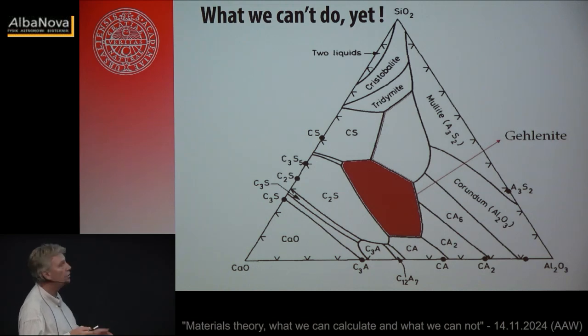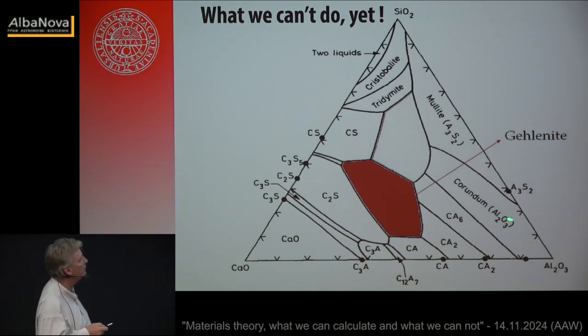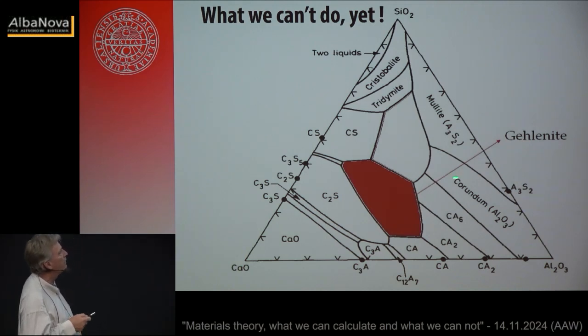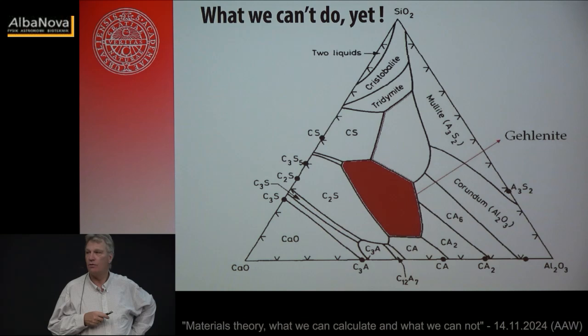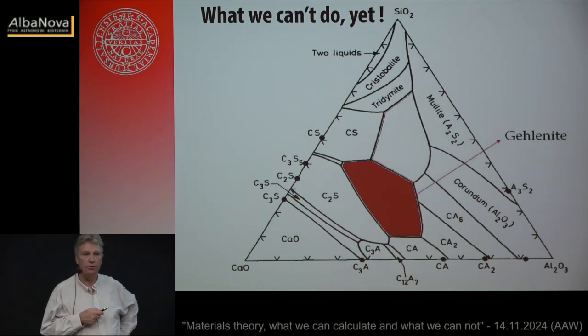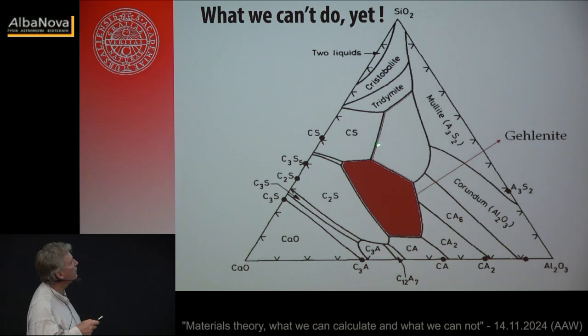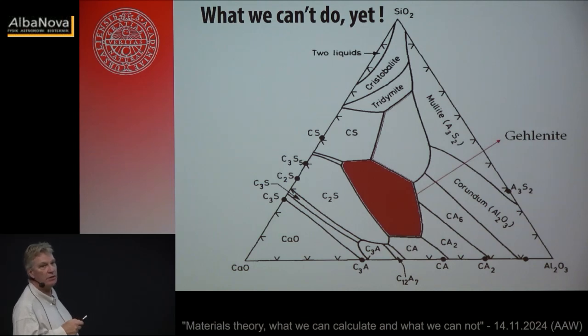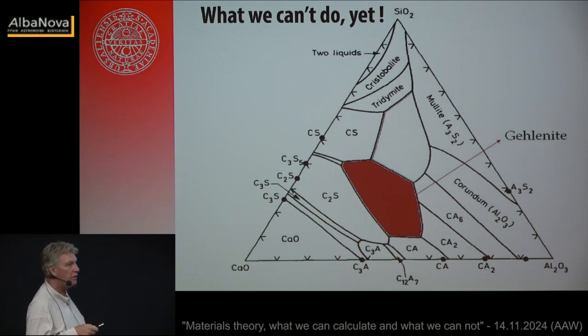You mix, you stir, you cook, and anneal for a long time, and then you do X-ray diffraction, and you say, oh, okay, it's corundum here. So very time-consuming, very accurate measurements have to be done. Of course, it would be fantastic to be able to do these things from DFT, to maybe point to, well, there's a little pocket here that you have missed in the experiment, so you should look there. But the accuracy we have in these functionals, in these calculations, is not good enough, not by a long shot, I would say, to even be close to relevant when it comes to looking at a phase diagram like this.